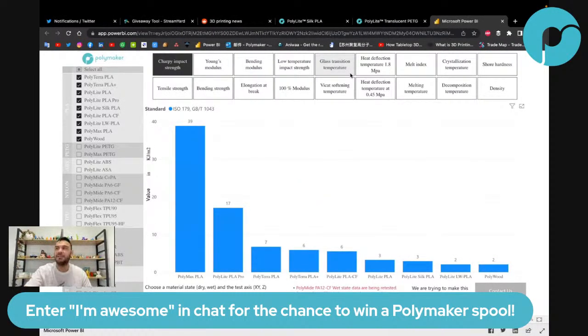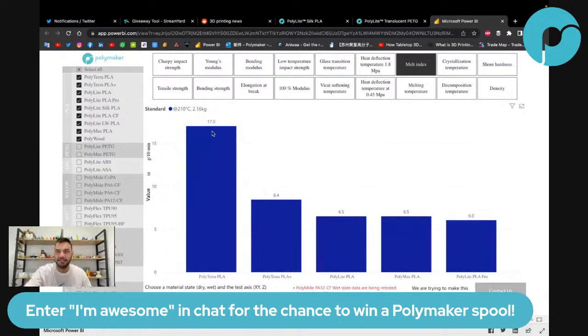Because remember that PolyTera PLA has an extremely high melt index. You remember that PolyTera PLA here? 17 gram per 10 minutes compared to the other one. So at 210 degree with a pressure of 2.2 kg, you can extrude 17 gram every 10 minutes with PolyTera PLA PLA. Rather than regular PLA, you can only extrude 6.5. So less than half for Polylite PLA. So definitely, if you're looking for high-speed printing, you should get PolyTera PLA PLA.